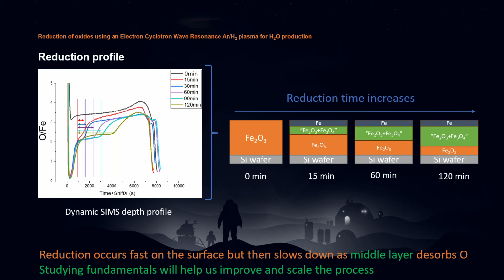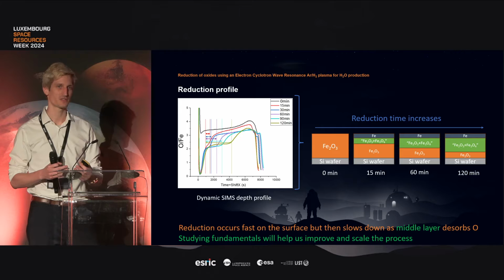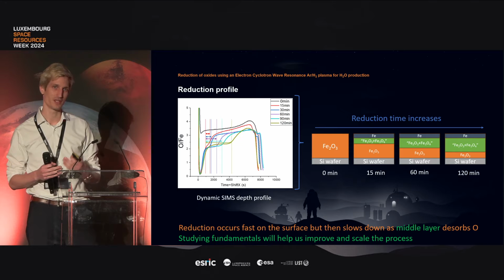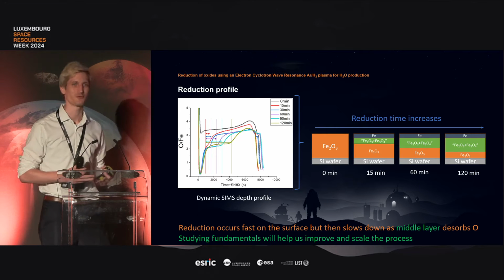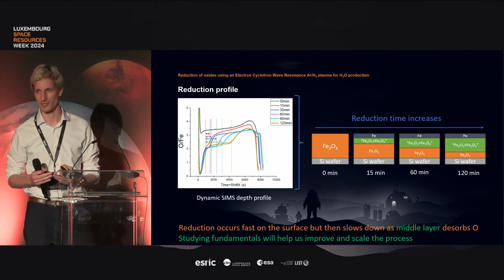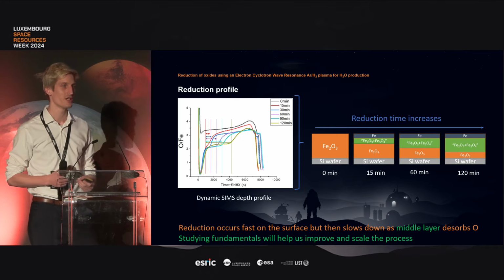We went further and we performed some SIMS depth profiling of the material. On the left, what we are seeing is the oxygen over iron ratio of various samples that have been reduced at various times with hydrogen plasma, but it's more useful if you refer to the right part, which showcases the model that comes from it.